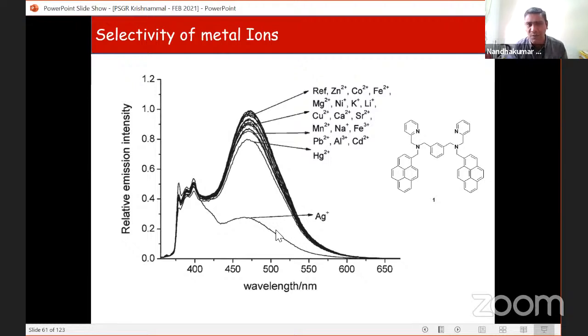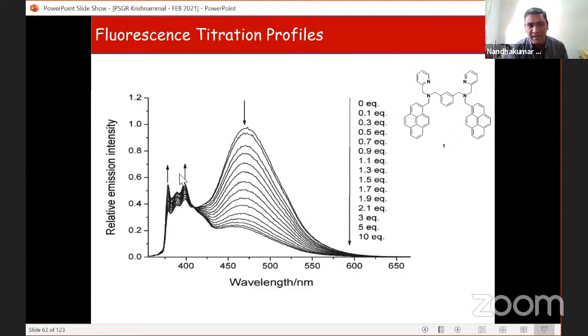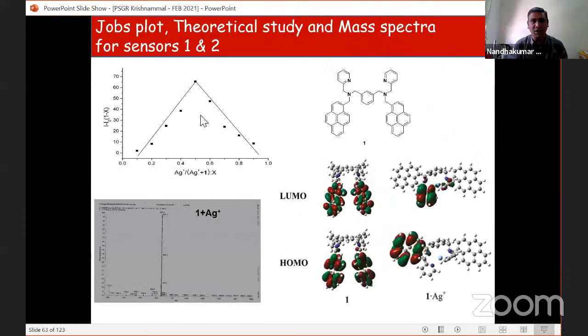So this is highly selective only for silver and not for other metals by fluorescence. You can see here the monomer enhances, but the excimer quenches. So this is the mechanism here. Monomer enhances and the excimer quenches, and we recognize silver when we compare to the other metals. So these are all the basic calculations, the Job's plot, the Benesi-Hildebrand plot to find the association constants and limit of detection, etc., and it is supported by theoretical HOMO and LUMO studies, and also by mass spectroscopy. This is the exact peak of the sensor with silver ions.